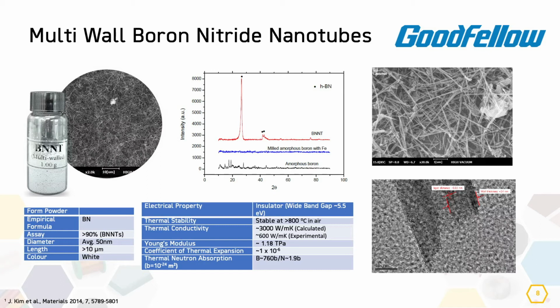This powder form of boron nitride nanotube has been produced by ball milling, actually crystalline ball milling of a boron source, using stainless steel. And keep in mind, stainless steel vessels and balls. All right. So you have a source of iron and a source of boron crystalline powder. From the XRD, we can see the amorphous boron in the beginning. So by ball milling the boron, we are resulting in an amorphous boron.